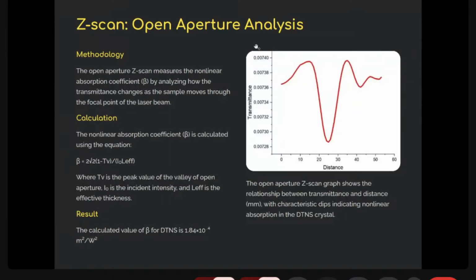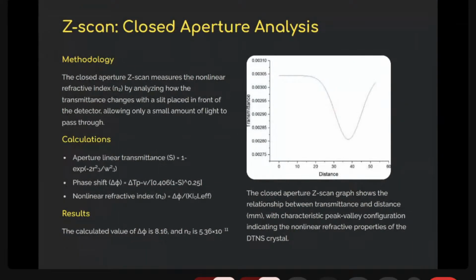As you can see, this is the open aperture graph, and from the graph we calculated beta. Beta is equal to 1.84 into 10 to the power minus 4 meter per watt square. That is the nonlinear absorption coefficient. And from closed aperture, we calculated the refractive index, which is 5.36 into 10 to the power minus 11.